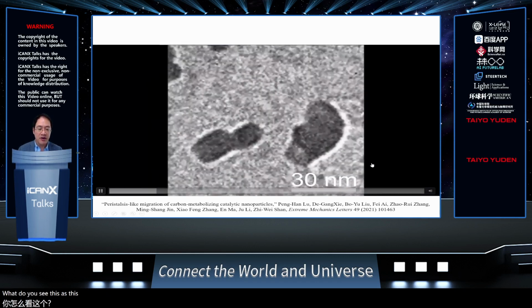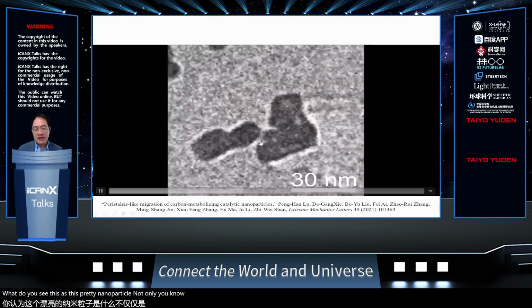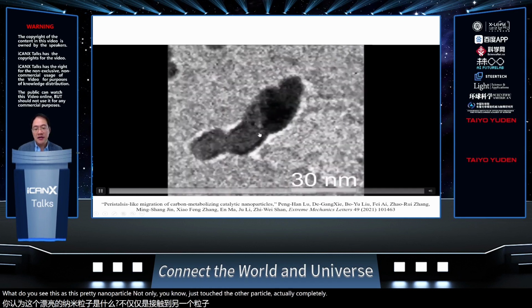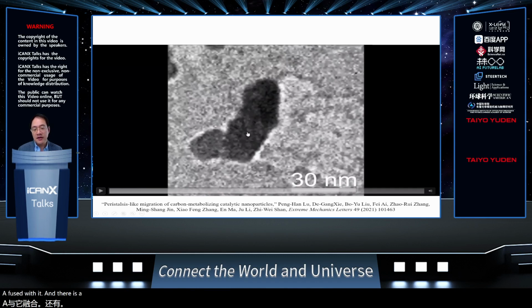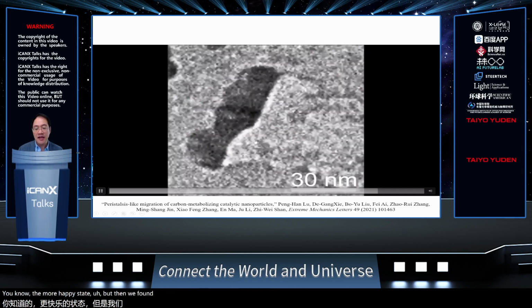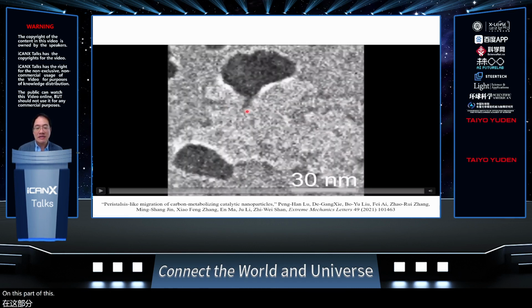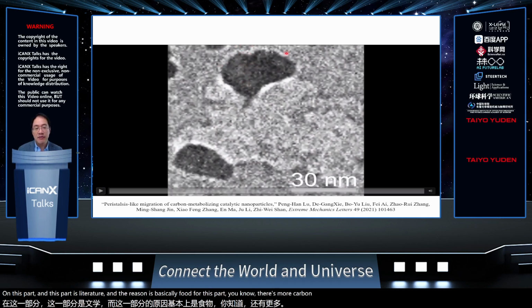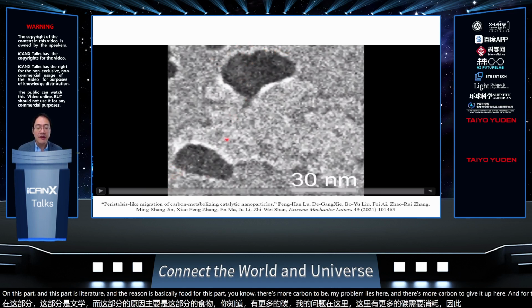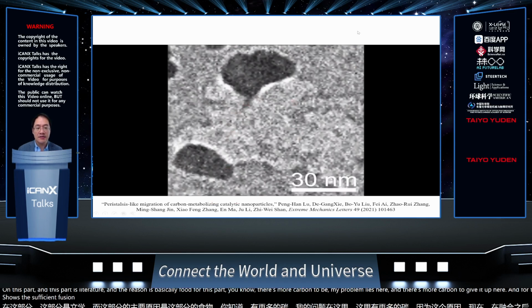And to show that this Ostwald ripening is delayed, we have another example where what you see is this palladium nanoparticle not just touching the other particle, it actually completely fused with it. I mean, it's basically one particle. So according to the traditional Ostwald ripening theory, this should be the more happy state. But then we found that later, this part and this part split. And the reason is basically food. There's more carbon to be metabolized here, and there's more carbon to be metabolized here. And for that reason, after the fusion, there is a fission. So this shows this fission-fusion balance.